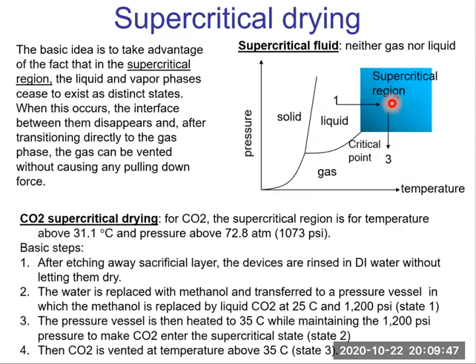Then we decrease the pressure. Right? We go downward by decreasing the pressure while maintaining the temperature. So the supercritical phase transits to gas phase, from state two to state three. With this process, we can see that the liquid becomes a gas without involving an air-liquid interface. It goes through the supercritical region. We use a supercritical phase as an intermediate phase. So there will be no capillary force during supercritical drying, and thus no stiction.